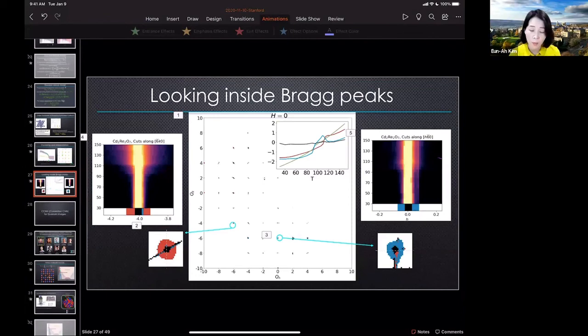There is also a Raman signature that was consistent with this kind of Goldstone mode fluctuation. So that's why we are interpreting it this way. There are several things: the temperature range over which we see the diffuse scattering, the form factor where we see or don't see the diffuse scattering, and how this lines up with the Raman scattering study that was specifically after finding that fluctuation. That's how we deduce that this seems to be Goldstone mode fluctuation.